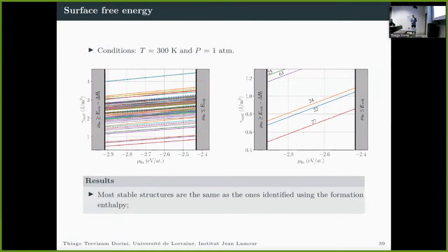So here we have the first results for all 114 structures at a temperature of 300 Kelvin and 1 atm. If we zoom in on the most stable structures, it is interesting to notice that the structures that have the lowest formation energy usually also present some of the most stable surface free energy, with a few exceptions, such as structure 27